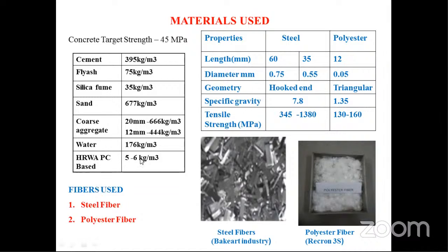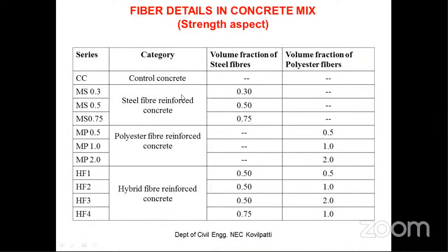A high range polycarboxylic ether based admixture has been used, and this table shows the fibers used in the test: steel fiber and polyester fiber. I have adopted hooked end mechanical fibers. It is a very good geometry, providing proper anchorage to the composite during crack resistance. These properties are essential when fixing the volume fractions of the fibers. So these two fibers have been added, and these are the series of mixes I have adopted. I have adopted 4 series of concrete mixes: control, steel fiber, polyester fiber reinforced concrete, and hybrid fiber reinforced concrete. And these are the volume fractions.